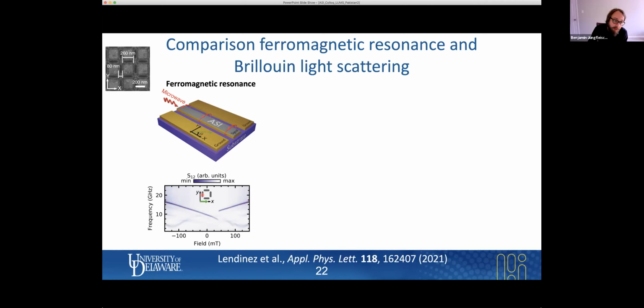Now, what about these elements which are patterned perpendicular to the external field direction? Well, in this case, if the field is strong enough, we can pull the magnetization from the easy axis, which is now in the y direction. We can pull the magnetization in the x direction for high magnetic fields. And in that case, we again have an angle of 90 degrees between the Ørsted field and the magnetization. So we get some torque. And this is what we see over here.